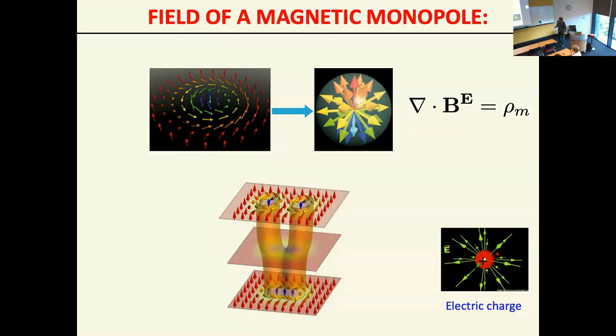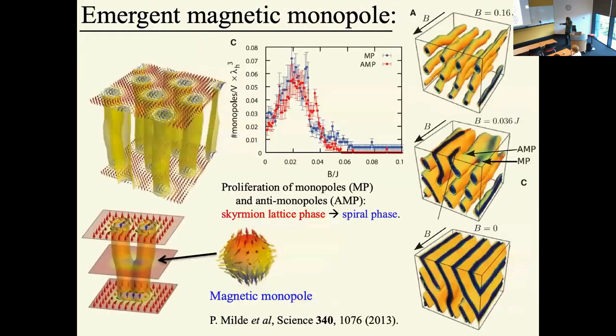So monopoles can be seen in condensed matter. Okay, here's a simulation, not mine. This is from, again, Munich. They did a simulation of these skyrmion tubes and started applying a magnetic field. When there's no magnetic field, you have lamellar structures of spins. Then they become joint tubes, and then the tubes separate. So in this region, you have a lot of such structures, and you see monopole, anti-monopole creation. Means points where the emergent magnetic field is radially outward. Okay.